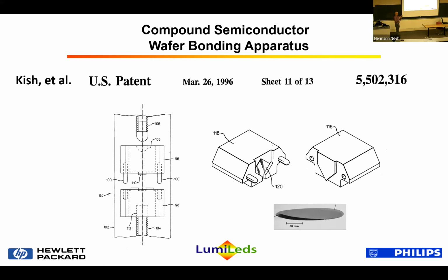Also, very importantly, we developed a way of holding the wafers so they could be held separate from each other and not have to be in contact before they were bonded. And so we could vary when the wafers went into contact. And then, I talked about not having wafers that were flat. Well, this gives you some example of what non-flat could be. This is a gallium phosphide wafer that is prior to bonding an LED set of layers where we removed the gallium arsenide substrate from it. So you're not just talking about variations in angstrom level RMS, you're talking about potentially having to deal with significant bow as well in the wafers.